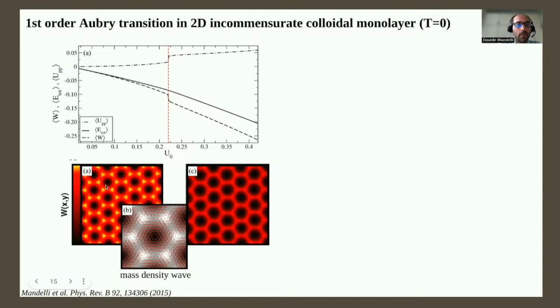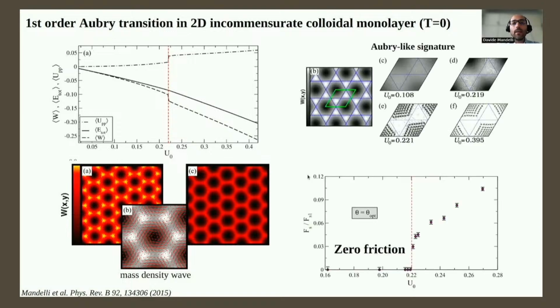So here we see a snapshot on the left below the critical point where there are still particles on top of the maxima of the substrate potential, as shown by the presence of these bright yellow dots, while on the right we see a configuration obtained above the critical point where these bright spots have disappeared, and we have much larger black regions that correspond to local commensuration with the substrate. So this is a clear sign of an Aubry-like transition also in the colloidal monolayer, and we have other signatures. First of all, friction drops to 0 below the critical point, and then it jumps to a finite value above the critical point. And what I'm showing here is a more detailed analysis regarding the occupation of the maxima.